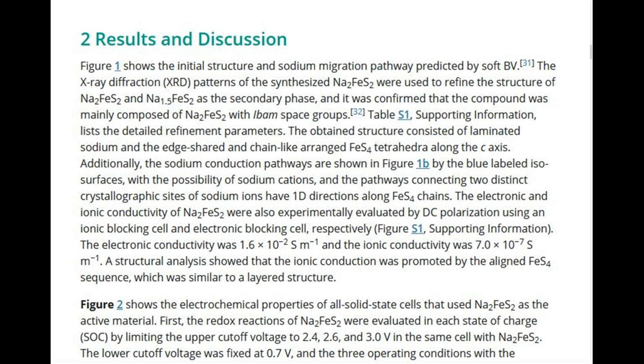The electronic and ionic conductivity of Na2FeS2 were also experimentally evaluated by DC polarization using an ionic blocking cell and electronic blocking cell, respectively, Figure S1, Supporting Information. The electronic conductivity was 1.6 × 10^-2 S m^-1 and the ionic conductivity was 7.0 × 10^-7 S m^-1. A structural analysis showed that the ionic conduction was promoted by the aligned FeS4 sequence, which was similar to a layered structure. Figure 2 shows the electrochemical properties of all-solid-state cells that used Na2FeS2 as the active material.